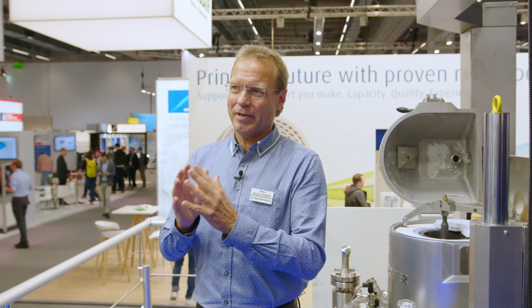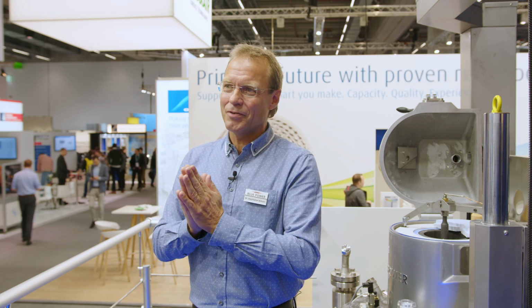Then to acquire and accomplish the higher temperatures that we need for platinum was another long story and process. We had to identify the right ceramics based on zirconium oxide. These have the potential to stand the temperature range 2000 degrees and above that we need for platinum.